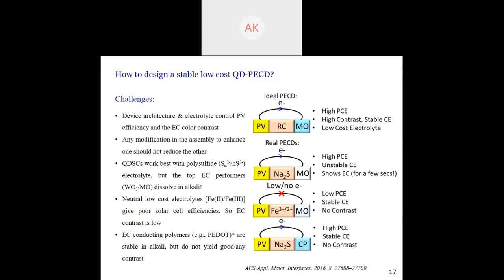Now, if we replace this alkaline electrolyte with a neutral, low-cost electrolyte, that is ferro-ferric, or iron 2 to iron 3, the solar efficiency becomes very poor. Though the transition metal oxides are very stable in these low-cost electrolytes, the electrons that flow through the external circuit are so few that you see no contrast. You can also have electrochromic conducting polymers like PEDOT that are stable in alkali and can also give high power conversion efficiency, but they do not yield any good contrast.